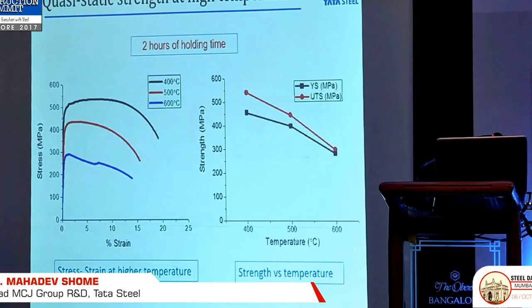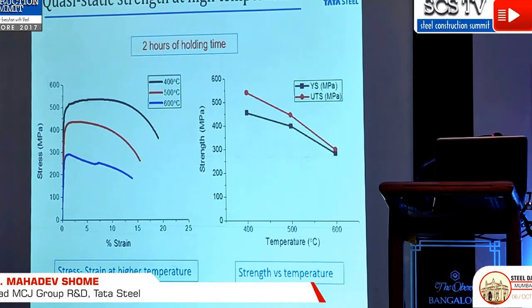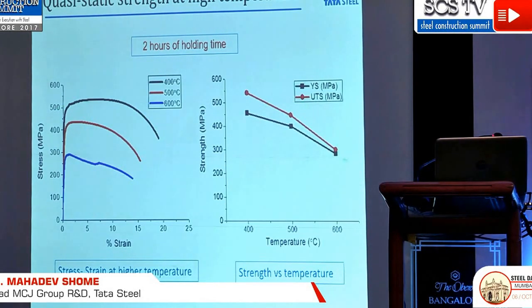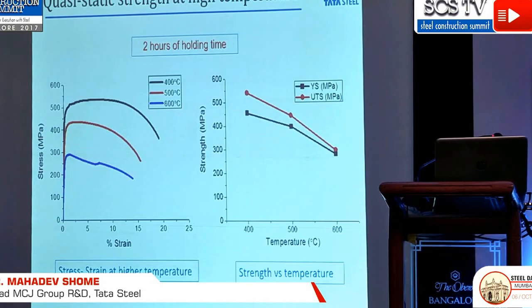So, there's always this competition or debate whether fire resistant paints are a good thing or material solutions are a good thing. But with this study, we have found that even if you put paint, it is not going to 100% retard heat transfer. Heat transfer is going to take place. In case of 600 degrees centigrade, the core would go up to 400 degrees centigrade. And how would the material behave at 400 degrees centigrade? So this figure says that the fire resistant plate would be able to sustain better yield losses than the paint covered material. So this is again the YS, UTS, which shows that it is up to the desired performance.